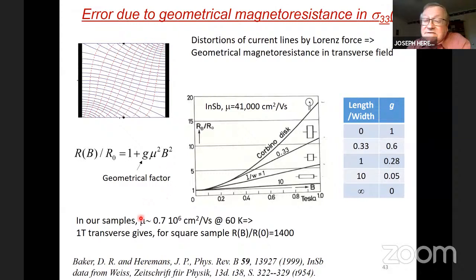But if we were to take this in our samples with a mobility of 700,000 at 60 Kelvin, one Tesla transverse, and we don't have a transverse, of course, it would give this geometrical effect to be 140,000%. So you see that would overwhelm everything.